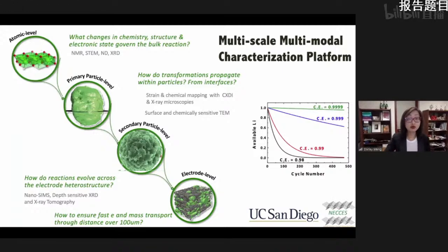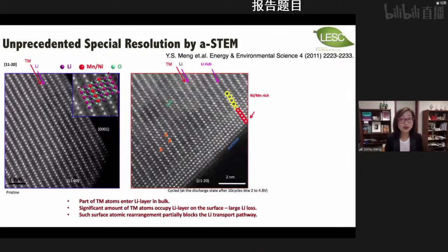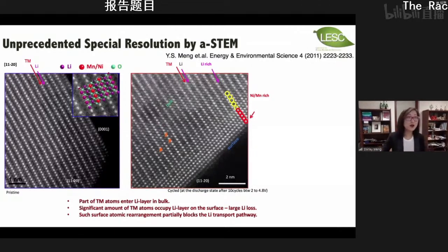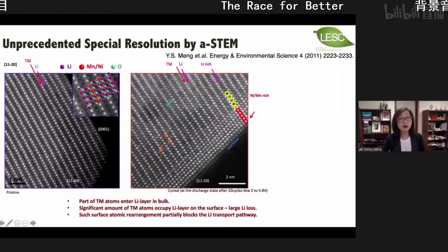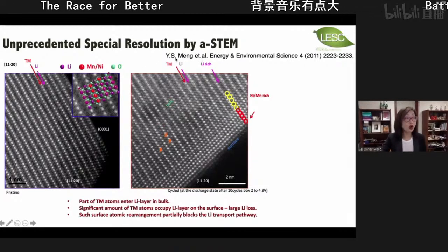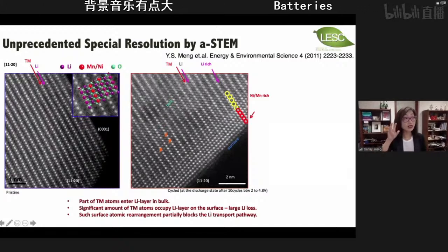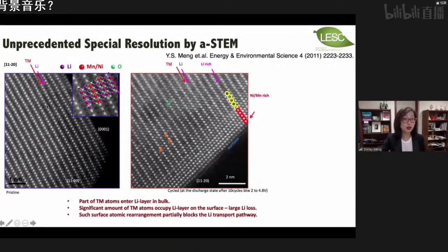So a good example to show you is my work, this is almost 10 years ago. I mean, it's exactly 10 years ago. But at that time, we were thinking about how we can utilize atomic resolution scanning transmission electron microscopy. I mean, 10 years ago, it was not very common for people to use this kind of so-called very fancy tools to look at the surface of high voltage cathode materials. And before and after, here you're seeing very beautifully synthesized cathode particles where you have a layered structure. We call it a layered structure by cartoon, and actually you can observe it in the microscope.